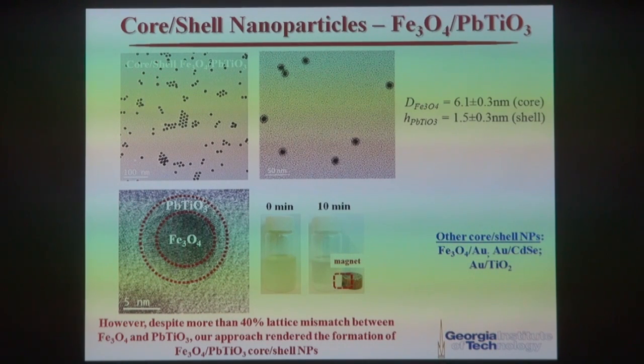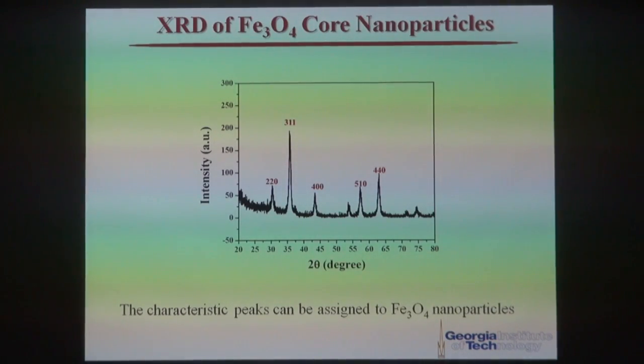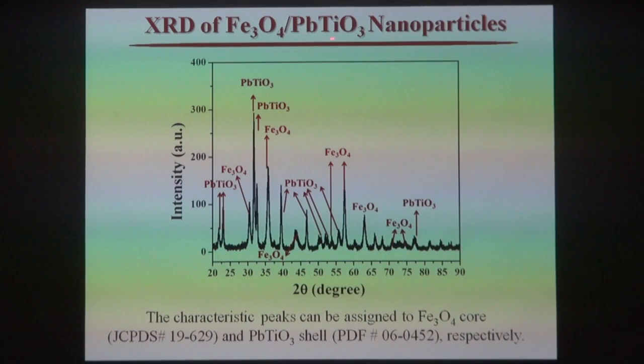shell. So here, after we make this core-shell nanoparticle, we want to verify that this particular approach indeed allows you to make core-shell nanostructures. So we did the XRD measurement, taking this magnetic iron oxide core capped with lead titanate shell as an example. For the magnetic iron oxide core, the XRD measurement shows the signature peaks coming from iron oxide. Now, once the particle surface is capped by the lead titanate shell, we see the coexistence of iron oxide and lead titanate, indicating the success in making these core-shell nanostructures.